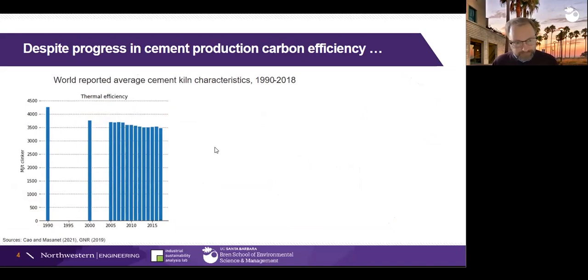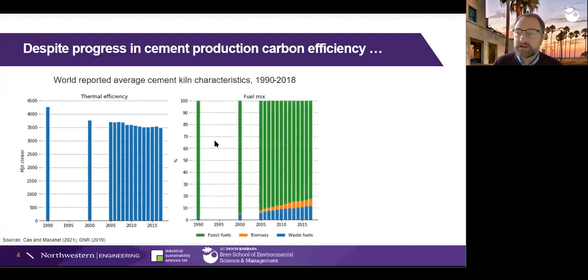And I want to acknowledge that the industry, particularly the cement industry, has made a lot of progress over the last few decades. What you're seeing here are reported thermal efficiency values in a global database called Getting the Numbers Right. It's a database that contains primary, reported data from hundreds and hundreds of cement plants around the world. And what we can see is that the thermal efficiency of cement kilns globally has improved quite substantially over the last 30 years, going from about 4,200 megajoules per ton of clinker to an average of around 3,500. So there have been significant efficiency gains due to a lot of investments made by the industry.